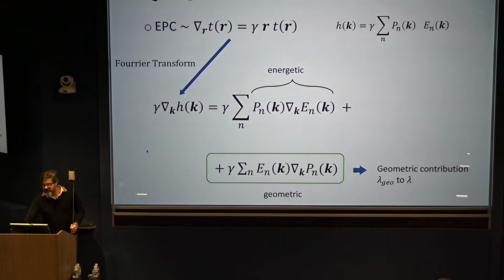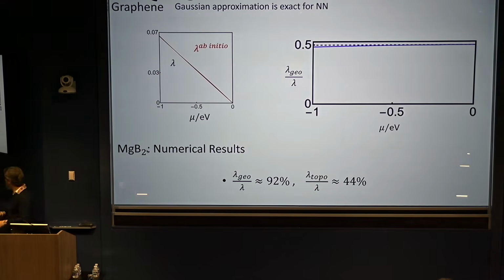If you put this, you ask which part of these two is more predominant. In graphene, for example, doped graphene, you can do an electron-phonon coupling. I'm not claiming TC here, just electron-phonon coupling. They're half-half. In MgB2, again, what I showed you before comes out here. The geometric part is 92% of this thing.